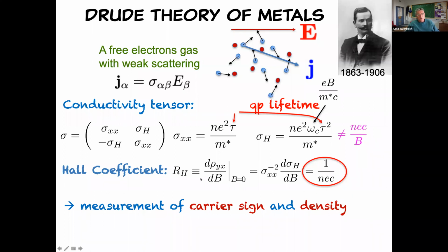But there is something that we'll show later on that survives even much more complicated Hamiltonians or much more complicated systems. And that is that the Hall coefficient, as you can see, does not depend on any dynamics. It doesn't have things like lifetimes and masses which enter time-dependent phenomena. It just measures density, which in a sense is like a thermodynamic quantity that you get from derivatives of the free energy. And this actually is a property that I have shown in my formulas is generalizable. So the question will be answered later on in this talk.